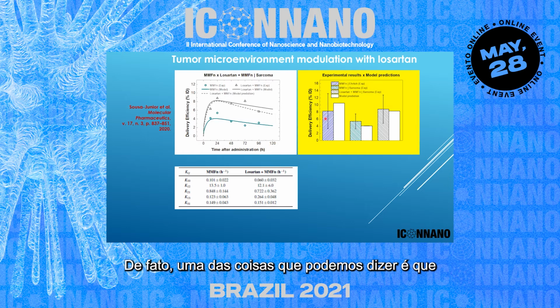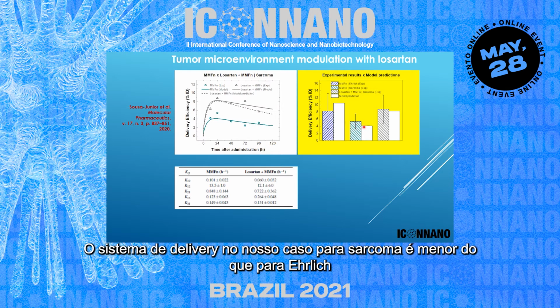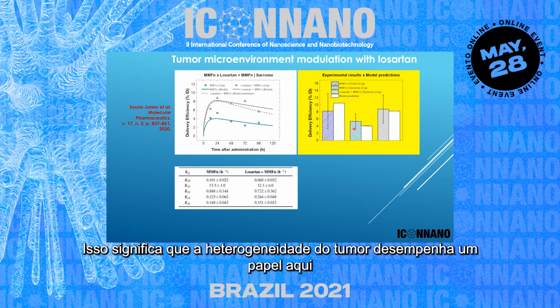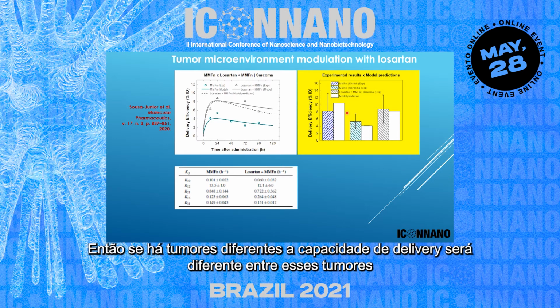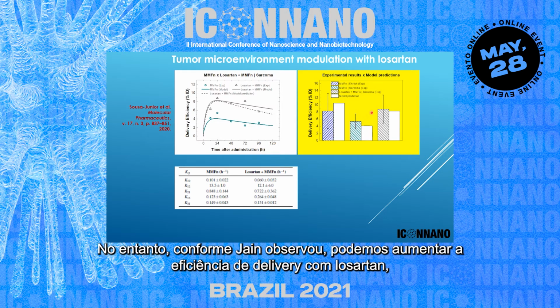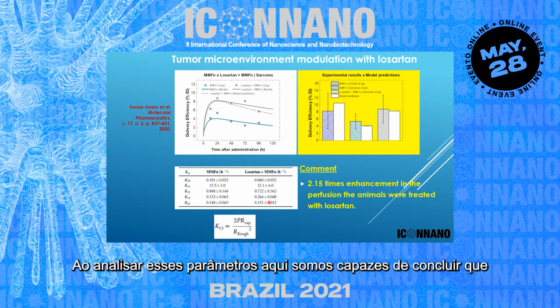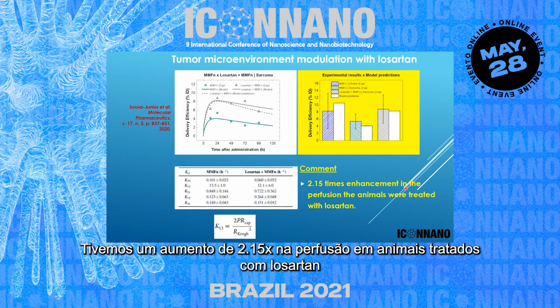In fact, one of the things that we can say is that the delivery efficiency of our case here, which is sarcoma that we are showing here, is lower than the case for Ehrlich. So this means that the tumor heterogeneity plays a role. So there are different tumors, and the capacity to deliver would be different in those two tumors. However, it is clear that we can enhance, as Jain observed, with losartan, the delivery efficiency of the nanocarrier. And by analyzing those parameters here, we are actually able to conclude that we had a 2.15 times enhancement in the perfusion of the animals when treated with losartan.